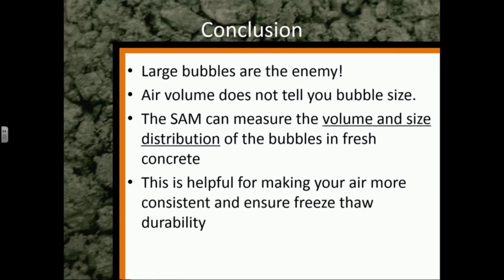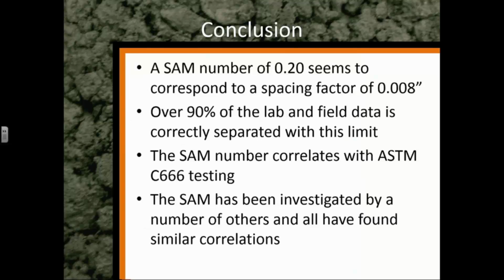So in conclusion, large bubbles are your enemy. Air volume does not tell you about bubble size, but the SAM can measure the volume and size distribution of the bubbles in fresh concrete, and this is helpful for making your air more consistent and ensuring freeze-thaw durability. A SAM number of 0.20 seemed to correspond to the spacing factor of 0.008, and over 90% of the lab and field data is correctly separated with this limit. The SAM number correlates with ASTM C666 testing, and the SAM has been investigated by a number of others, and all have found similar correlations.